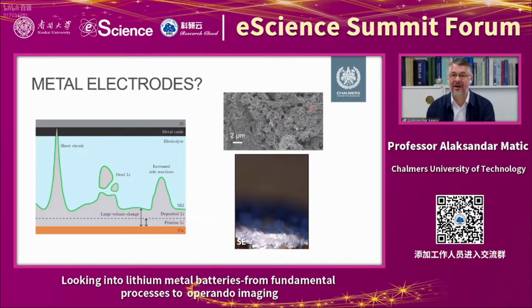And of course, this is not what we would like to have. On the bottom, you see something which looks pretty, but actually it's not very useful when it comes to a battery. And here we're depositing instead potassium. So this is potassium deposition. And you can see that when you deposit potassium electrochemically, if you are not careful, you get really this kind of dendritic growth with a very porous structure. It looks almost like a forest. It's a beautiful image. But of course, you would immediately have a short circuit in your cell if this was the situation. So these are the challenges we are facing when using metal anodes.